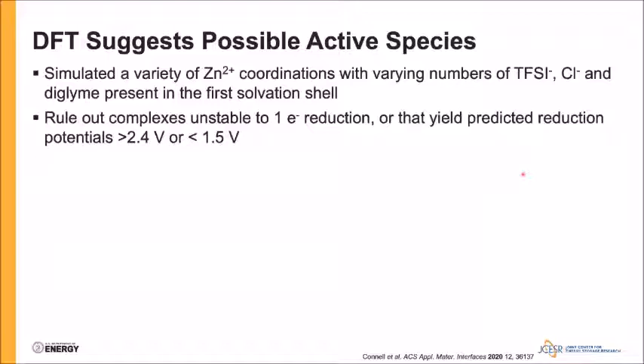And basically, in order to down select, we rule out any complexes that were either unstable to one electron reduction or that yielded reduction potentials outside of the window where we see any evidence of zinc metal deposition in our voltammetry. And what we find is several stable complexes, and I'll highlight a couple of them here.